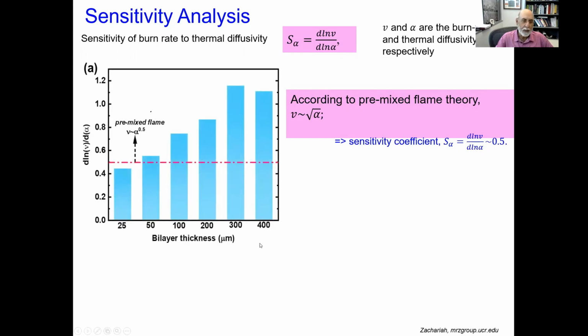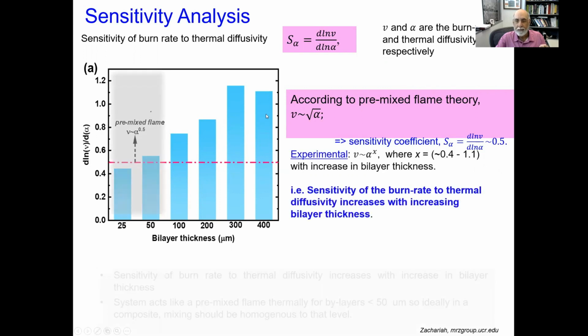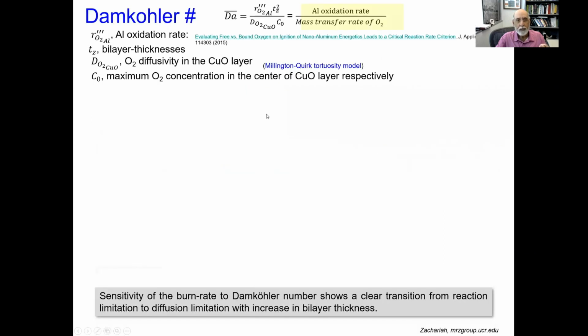And what do we see experimentally here is this is what laminar flame theory should be, and this is what we see. So when layers are under 50 microns, they act like a premixed layer. And when they are larger than that, now we're sort of mass and heat transfer limited, and there's more sensitivity in the sensitivity parameter. We can compute other things.